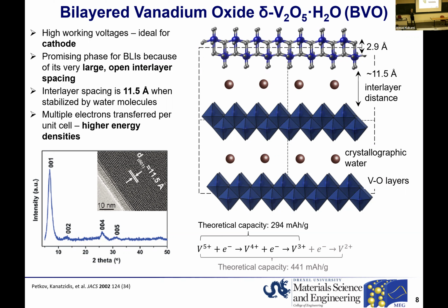This is a huge distance, and such a large interlayer region cannot be stabilized by van der Waals interactions only. In order to stabilize this large interlayer distance, we need some other species. We need some other forces that would hold these layers apart without collapse. And in the parent bilayered vanadium oxide, such interlayer species that help with structural stability are just water molecules. So water molecules reside in the interlayer region, essentially introducing some hydrogen bonding within the layer. And this helps with maintaining structural stability with such large interlayer distance.